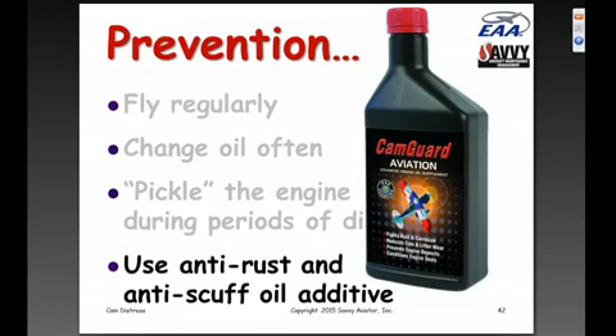And anti-scuff means that it helps prevent the cam and lifter interface from wearing during the start cycle after the airplane's been sitting for a while and the oil film has stripped off. So this is the additive that I use in my own engine. Incidentally, I'm in the process of tearing down one of the engines on my 310 finally. It's at 205% of TBO, and we pulled all the cylinders off and inspected all the lobes of the cam, and the cam and lifters are pristine after